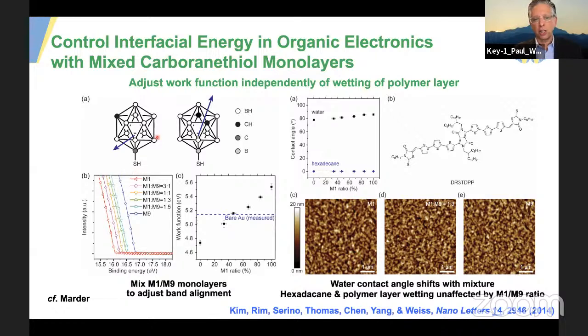And so what Jay showed was that with a monolayer that's mixed between these 2 layers, we could tune the band alignment by 1 eV, and each one of these points is 40 devices. We don't change the wetting properties of the polymer, we don't change its morphology, and we're off to the races. And the same ideas apply, for instance, when we make contacts to the transition metal dichalcogenides. We can choose the carborane that gives us the charge where we want it in order to get band alignment to the material. And the functionalization of these has been completely explored.